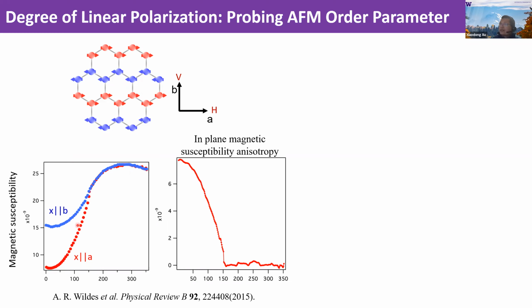So we took this data from the paper, then we extracted the difference of the magnetizability along the A and the B axis and plotted it as a function of temperature. These are the data we extracted from this paper and calculated from the left plot. You can see that this in-plane magnetizability anisotropy is really the order parameter. It's zero above the Néel temperature and starts to increase below the Néel temperature.